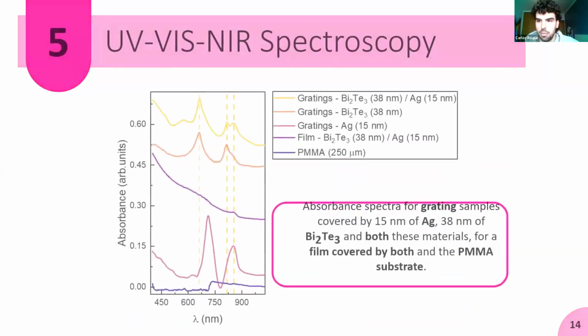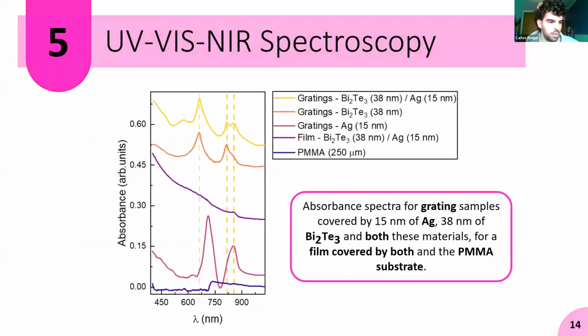Then we measured our samples for the different types of structure: only a substrate, then a film with both materials, a grating with both materials, and two gratings with one of them, to try to identify different contributions in the optical spectrum. Firstly, the PMMA substrate doesn't have any optical signal, as we were expecting, because it's highly transparent. Then the film exhibits increasing absorbance with decreasing wavelength, and this is present in the gratings. So this comes from the intrinsic optical properties of the materials and not from plasmonic events.